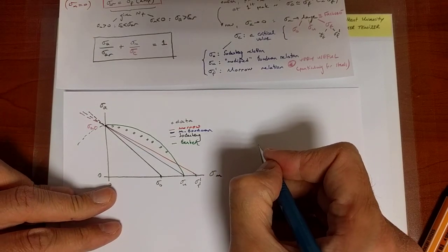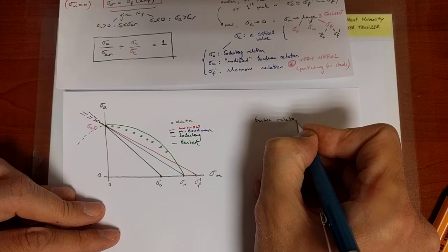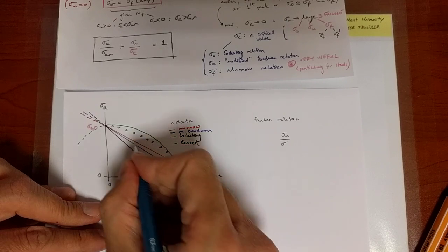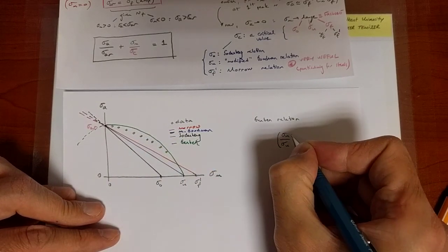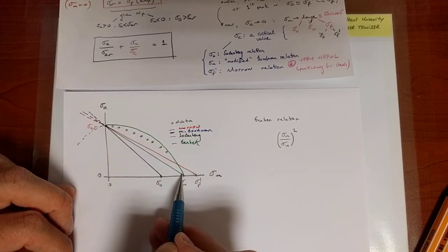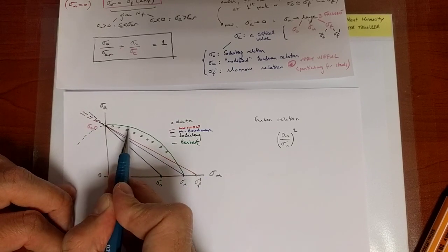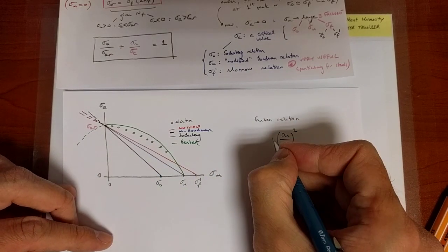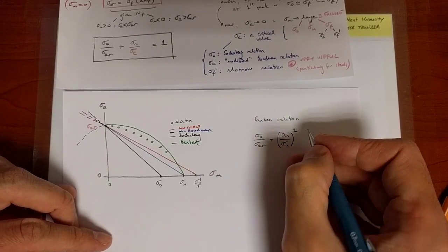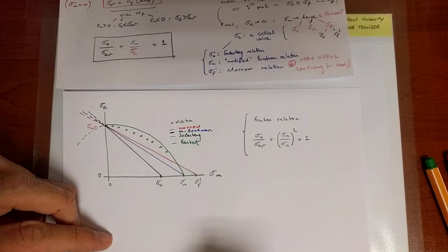Instead, what we're going to do is take the second one and add it with the intercept being sigma u, add it after squaring it. Because if I do that, I can get a curved line that is more reminiscent of the data. It still doesn't fit the data, notice, but at least it is curved and not straight. And the other part remains the same as in our old template. So that is equal to 1, another relation called the Gerber relation.